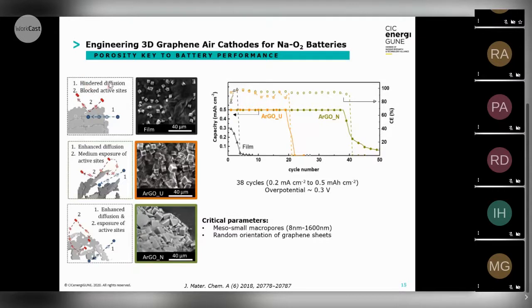And this is because, imagine a film where you don't have porosity, the oxygen needs to diffuse. So the oxygen diffusion is going to be hindered. And if we block the active site, the oxygen is not going to be reduced, or only in a small amount. That's the reason we only see some discharge product at really low capacity and low cycle life.